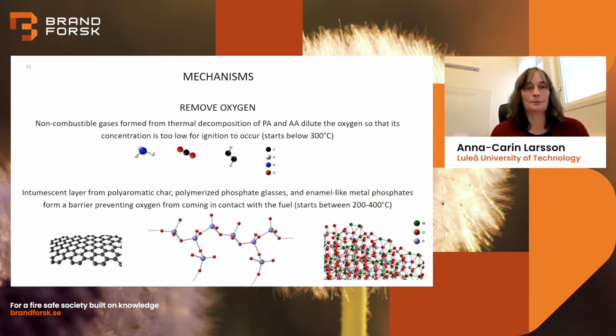We will also remove the oxygen. So those non-combustible gases formed when mainly the amino acid is decomposed, the ammonia and the CO2, they will mix with the oxygen in the air so that the oxygen will be diluted. So it will have so low concentration that it will be difficult to ignite the pyrolysis gases that still are there. And this starts below 300.